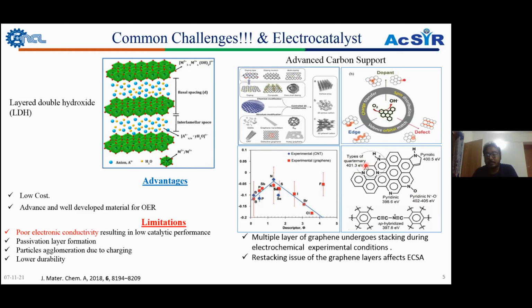So this is the nitrogen doped graphene substrate, but there is still an issue when we go for the graphene substrate: there is still no available synthesis procedure for single-layer graphene. There are commercially available procedures, but more than one layer can form. So during the electrochemical performance, there is a possibility of restacking of the individual graphene layers, which can suppress the performance during the electrochemical condition.